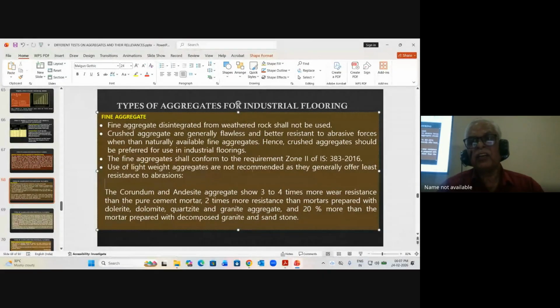Use of lightweight aggregates is not recommended as they generally offer least resistance to abrasion. For a typical example, corundum and andesite aggregates give 3 to 4 times more wear resistance compared to pure cement mortar, and 2 times more resistant than mortars prepared with dolerite, dolomite, quartzite, and granite aggregate, and 20% more than mortar prepared with decomposed granite.